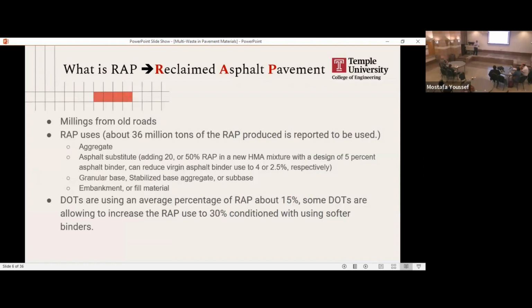RAP, as the name indicates, is reclaimed asphalt pavements. So these are pavements that were removed, and we're trying to incorporate them back into newer pavements. However, their properties, the asphalt specifically inside the RAP, has been exposed to a significant amount of oxidation that leads to significant change in its properties. Yet the aggregate inside that RAP is of good quality. So why use it in landfills or at a lower level or lower quality structures when we hopefully can use it for high quality structures like highways?